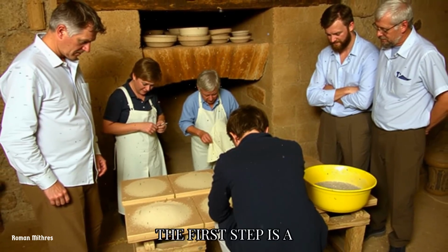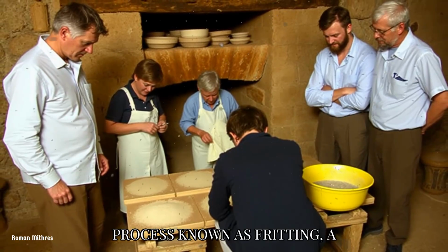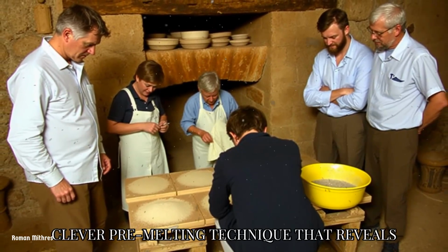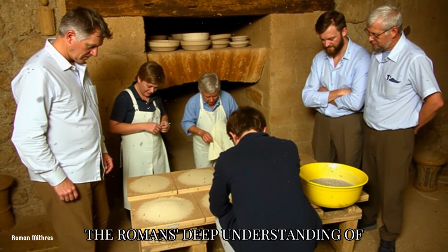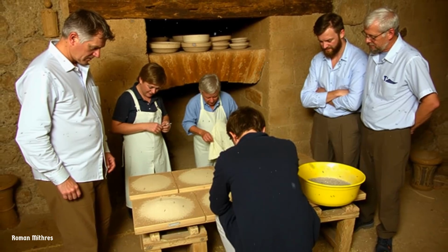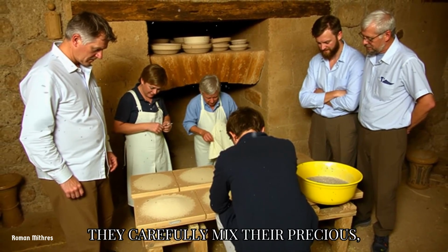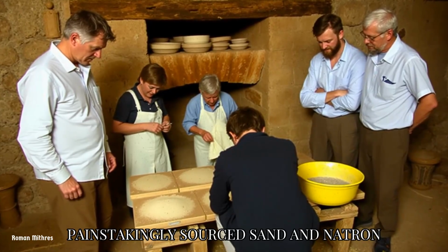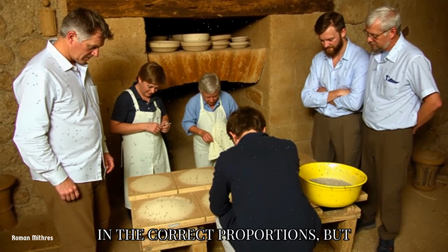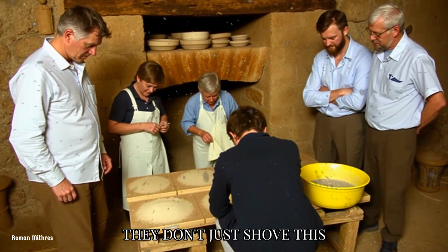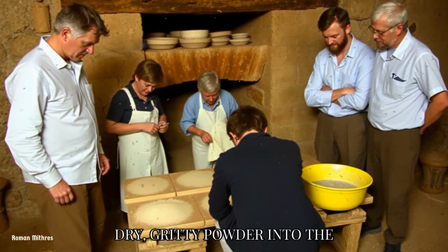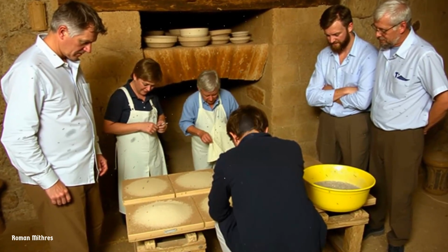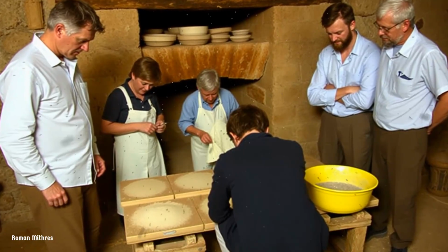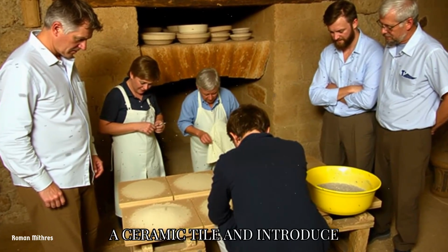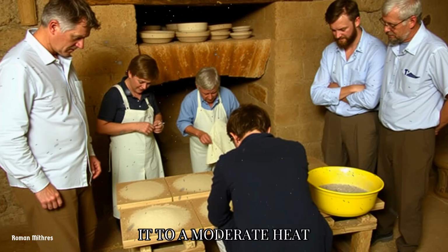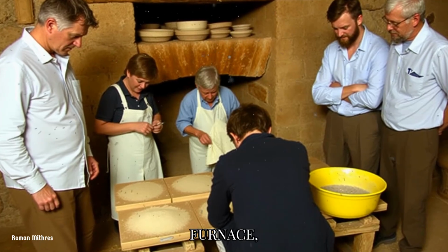The first step is a process known as fritting, a clever pre-melting technique that reveals the Romans' deep understanding of their materials. They carefully mix their precious, painstakingly sourced sand and natron in the correct proportions. But they don't just shove this dry, gritty powder into the crucible. Instead, they spread the mixture in a shallow layer on a ceramic tile and introduce it to a moderate heat at the front of the furnace.